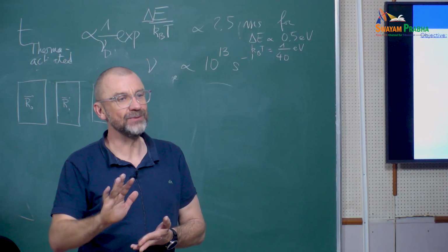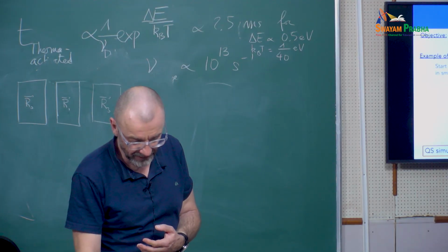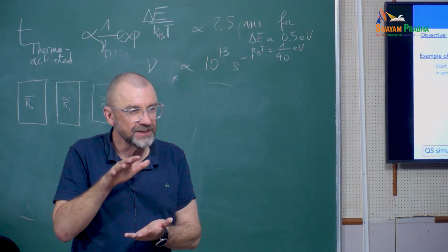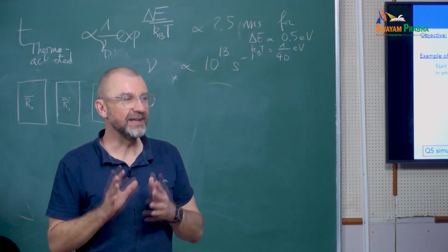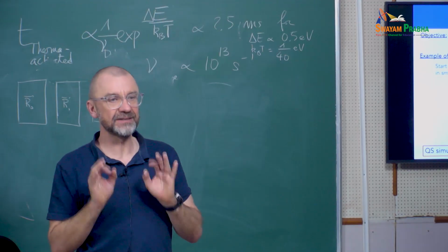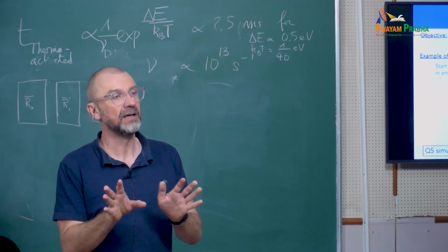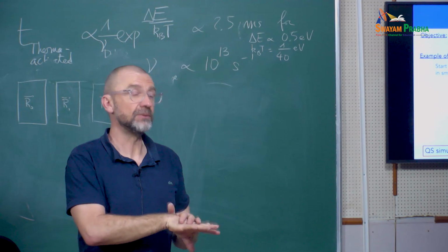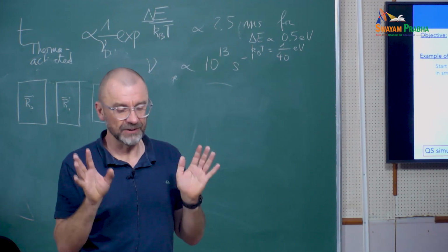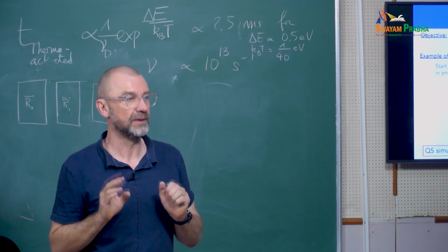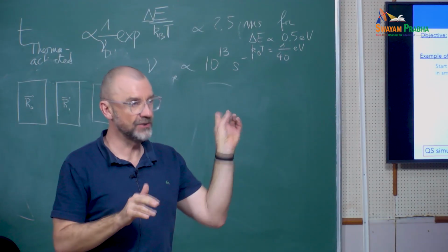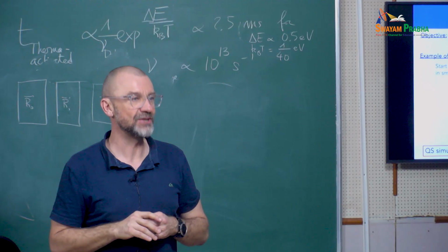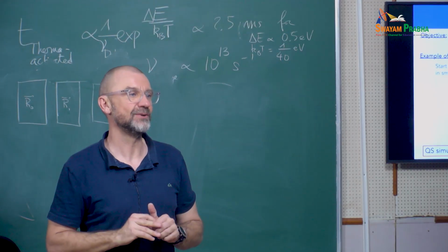So quasi-static simulation, I think I wrote it somewhere, is the limit of zero strain rate, but also zero temperature. So it's a weird limit, but it can be very useful, in particular in crystalline metals, but also a lot in glasses, for example. Many of the studies of the mechanics of glasses are done using quasi-static simulations. Zero strain rate, zero temperature.